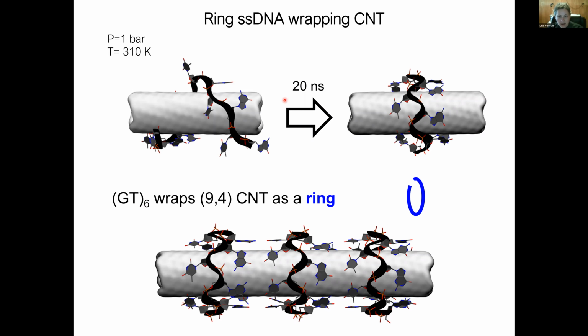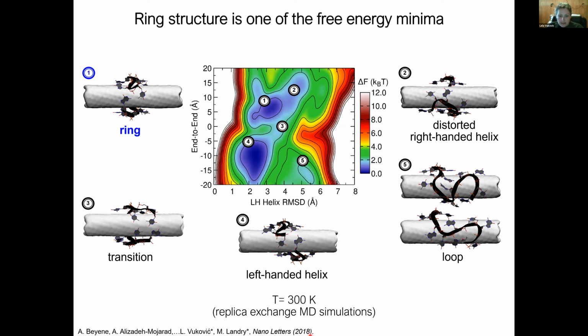In chemistry, we usually think this could be an accident, but if we can prove that this state of the system is a free energy minimum state, then we can be assured that the observation is the one that is going to repeatedly happen, no matter how many times we would test such a simulation. So the next thing we did is we used replica exchange molecular dynamic simulations, pretty computationally intensive, to calculate the free energy landscape of a system of a nanotube wrapped by GT6 DNA.